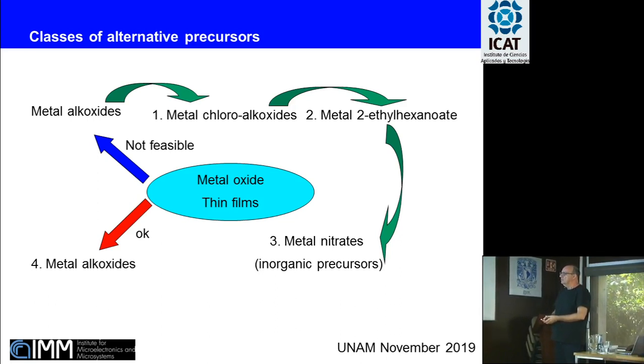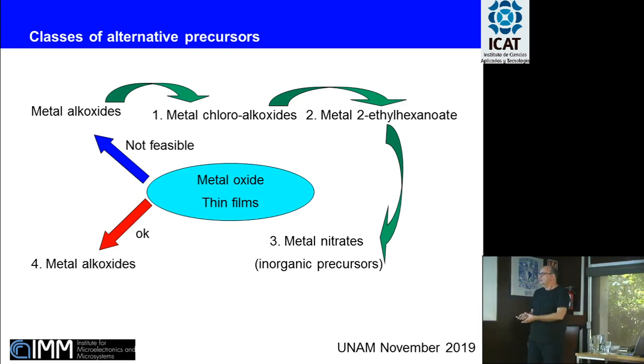So, if we have a metal alkoxide that does not have particular disadvantages, like titanium, we can use it very easily. We will see an example at the end. But, if it is not convenient, we will see the development of some alternative precursors. First, metal chloroalkoxides. When they are not advantageous, we develop another class of precursors, which are metal 2-ethyl hexanoates. When both these two classes are not useful, we will see how we can also use metal nitrates as a precursor, so simple inorganic precursors. So, let's start from the first class, the metal chloroalkoxides.